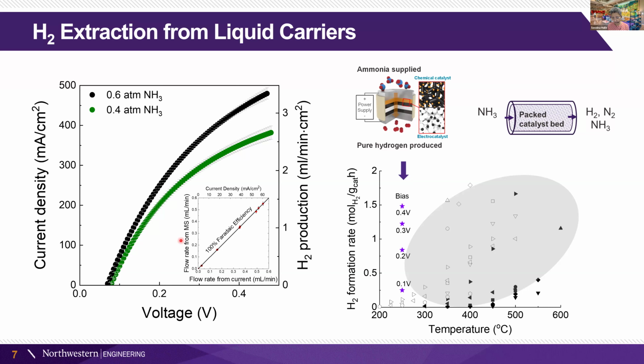And looking to the right, we see that if we compare the hydrogen that is generated per mole of catalyst, it is quite high compared to traditional methods of decomposing ammonia into hydrogen and nitrogen, which is to flow the ammonia past a packed bed catalyst. And those reactions happen at much higher temperatures. So you can see that sort of in the gray area. Those are all the typical results using packed bed catalysts.